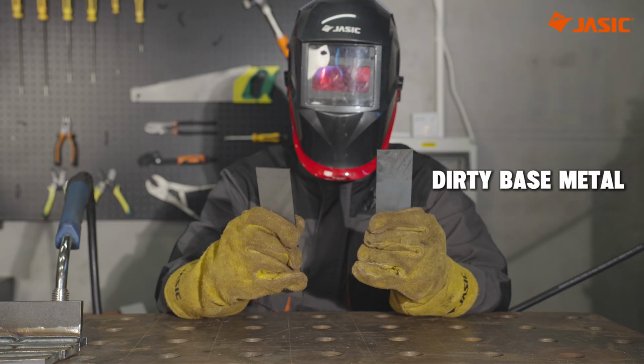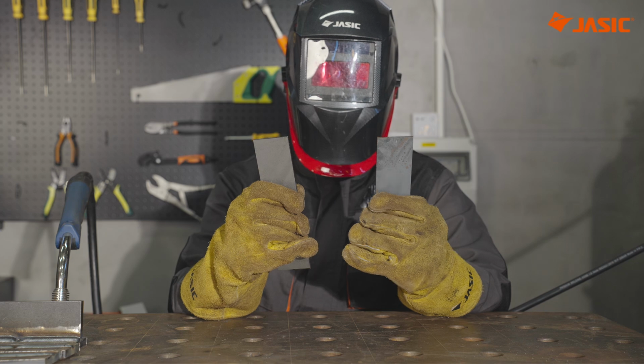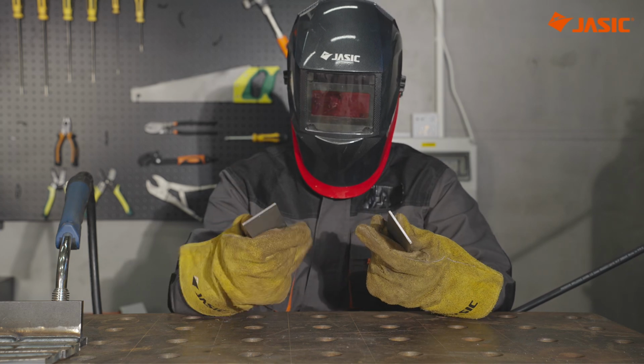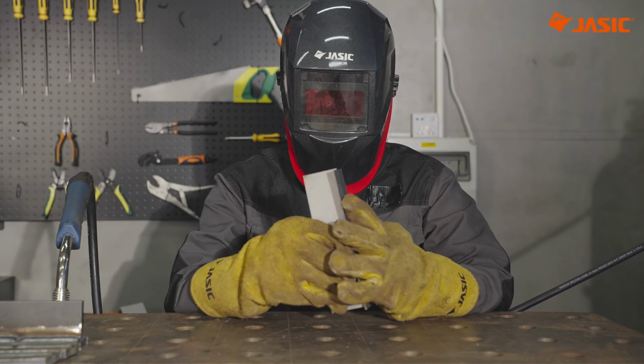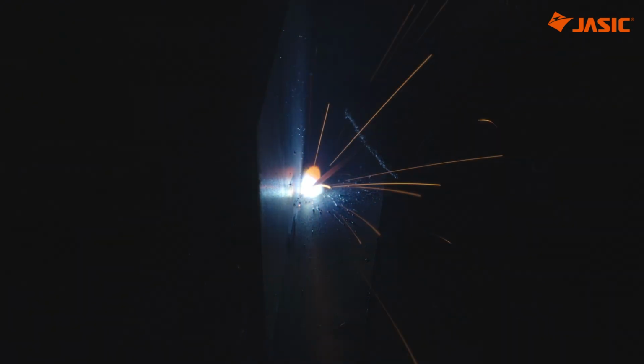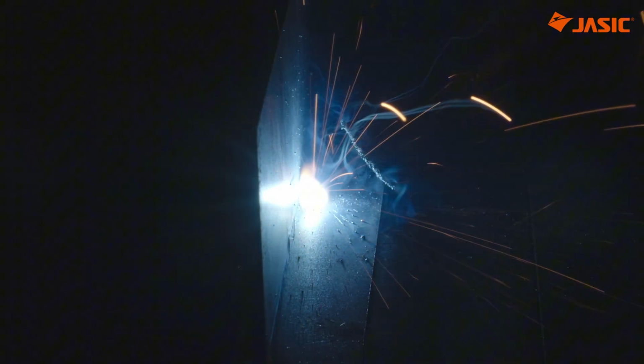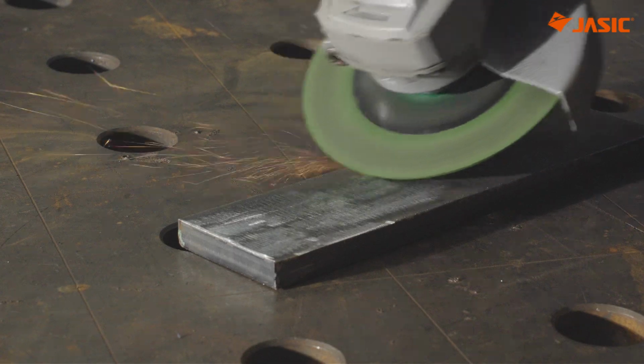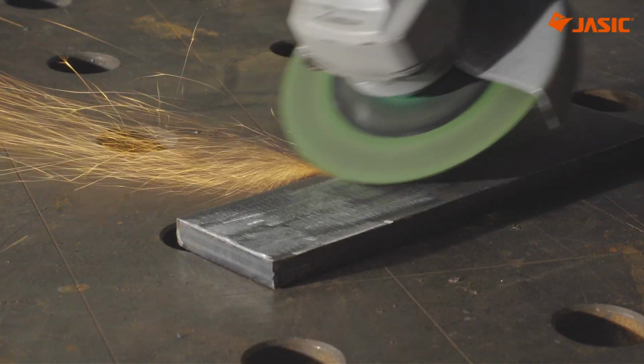Dirty base metal is another major cause of spatter. Oil, rust, moisture, paint, and mill scale all vaporize under the heat of the arc, creating gas bubbles inside the molten pool. When those bubbles burst, they eject molten metal and create spatter. Always clean at least 20 millimeter around the weld area before welding.